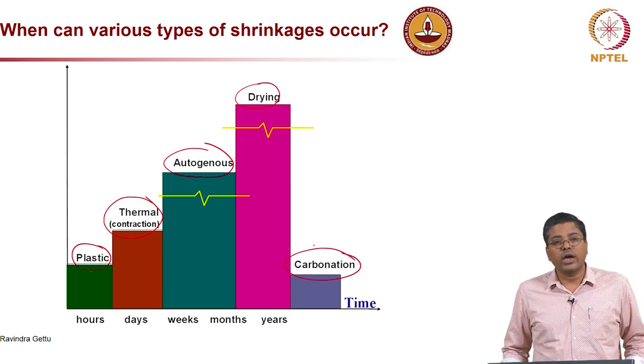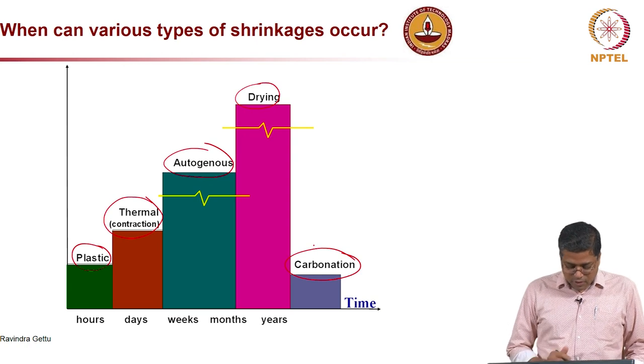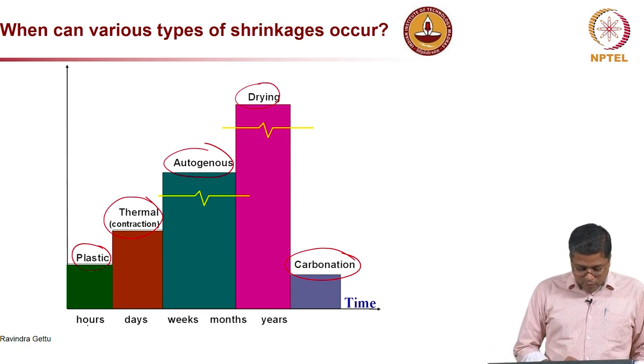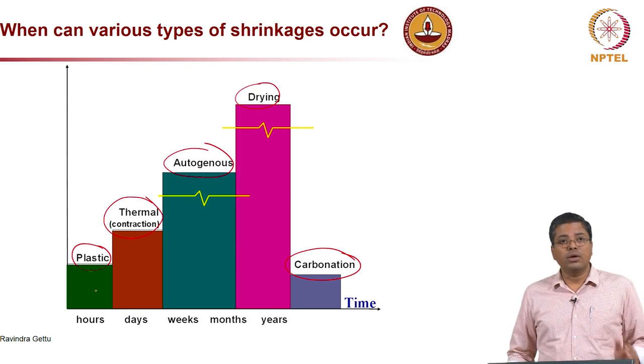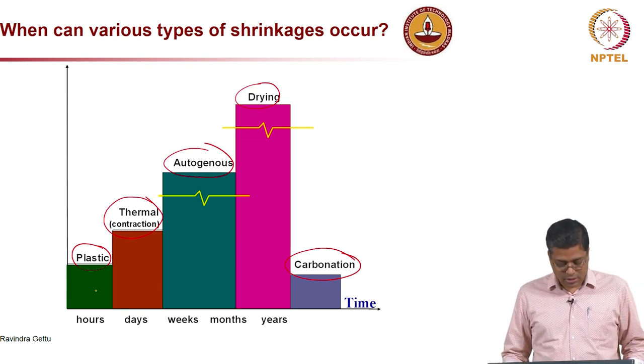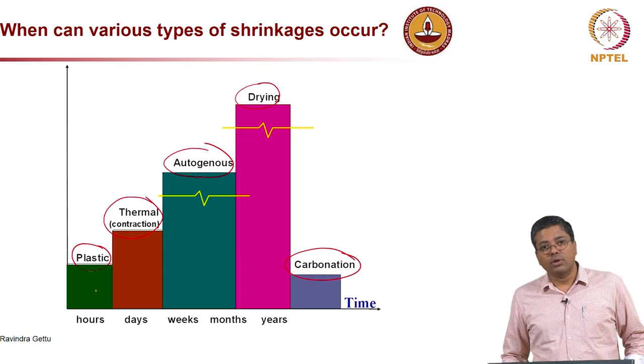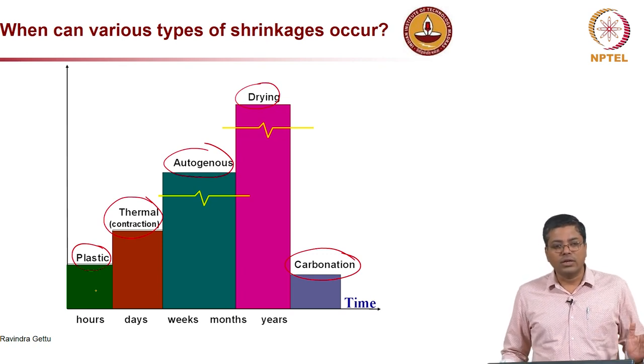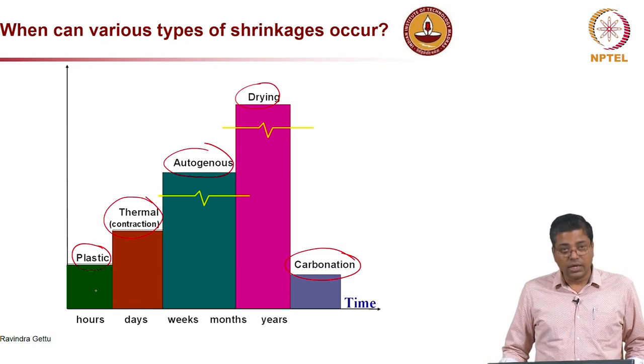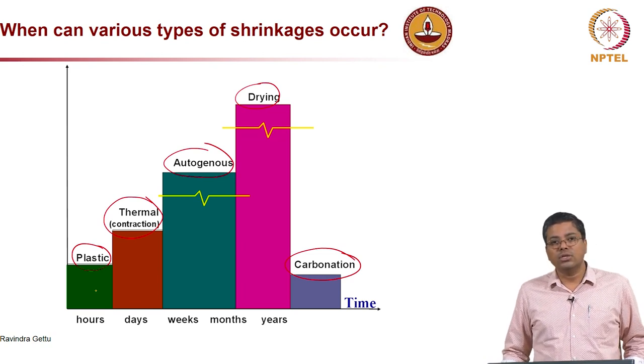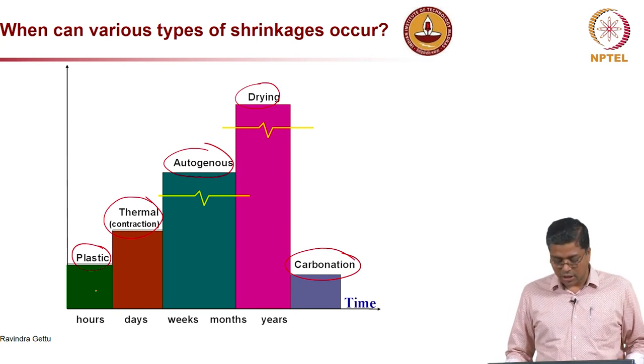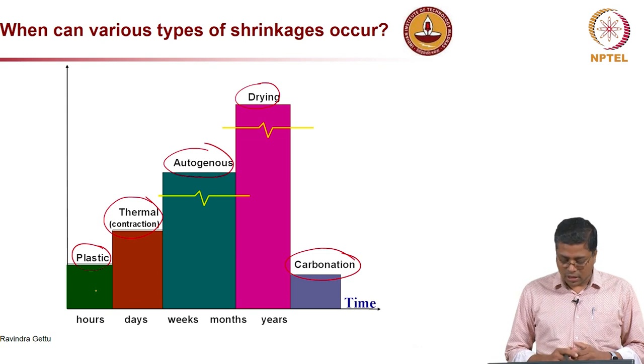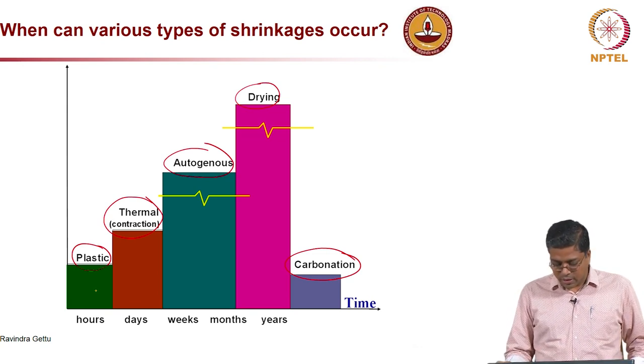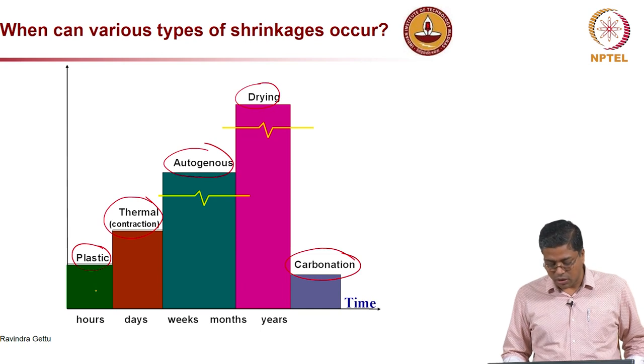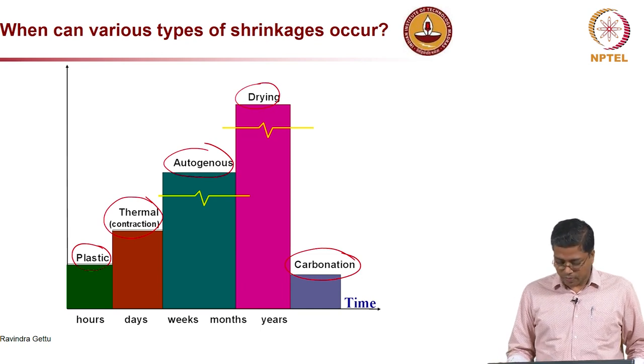These are the 5 different types of shrinkage which we will discuss in this lecture. And when do they occur? Mainly, plastic shrinkage happens in the first few hours, and then thermal shrinkage right after the final setting, and you can start seeing thermal shrinkage. And then autogenous shrinkage in the first few weeks, and then drying and carbonation shrinkage happen in the long run, or long term process, whereas carbonation shrinkage might take much longer than all the other 4.